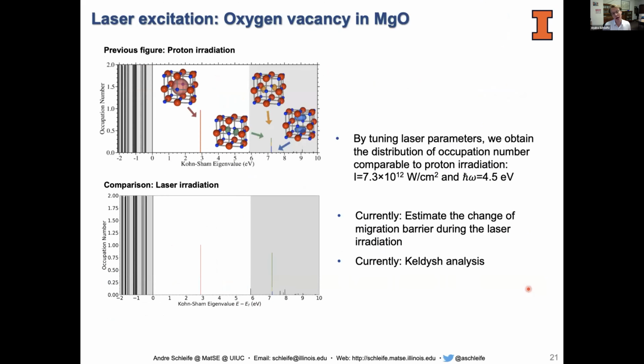And so one thing that we tried to compare to is an external electric field, or in other words, a laser beam. And in this case, this plot you've already seen, so I just show you the comparison, what the occupation number distribution is if we excite with a laser beam. In this case, we used a frequency slightly above to be able to excite the defect transition, and intensity like this one. And you can see that we see similar effects, right? The defect gets depopulated and the excited state gets populated.